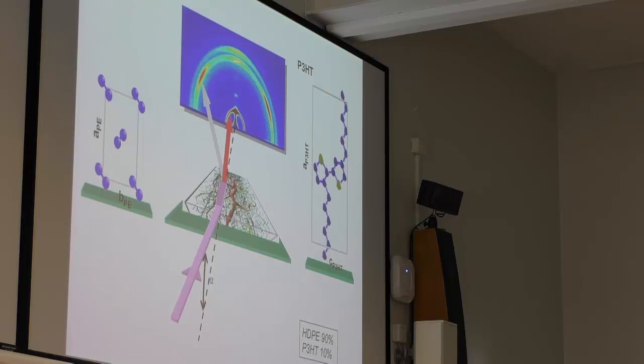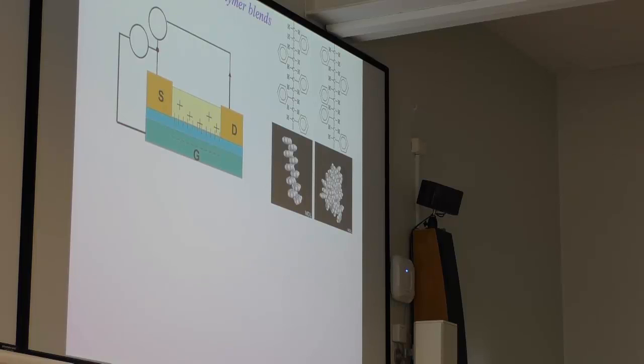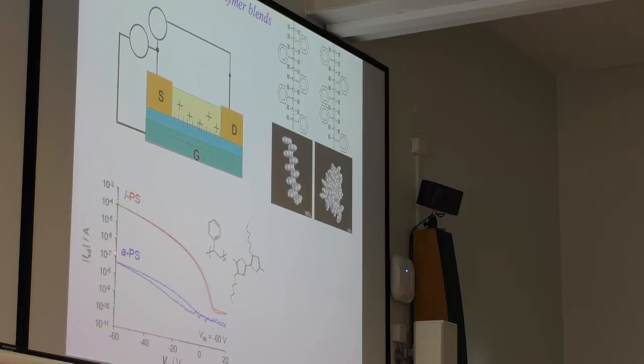And then when you look at the scattering pattern from this, these reflections you see here turn out to be from polyethylene, and these structures are from poly(3-hexylthiophene). And then the interesting part was that when this is correlated with the field effect transistor measurements, and with the use of both isotactic and atactic in different experiments, and clearly materials, so either highly ordered, so to speak, polystyrene or more amorphous material, the source drain current is 3-4 orders of magnitude different, right?